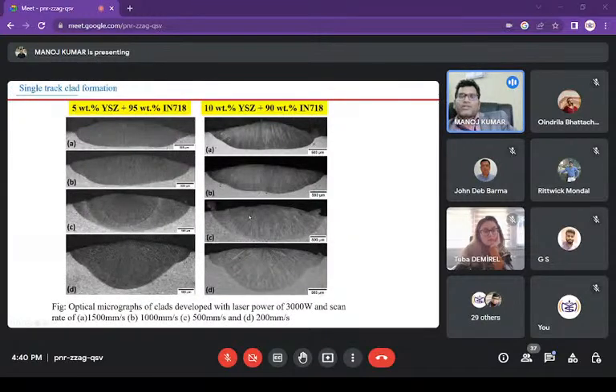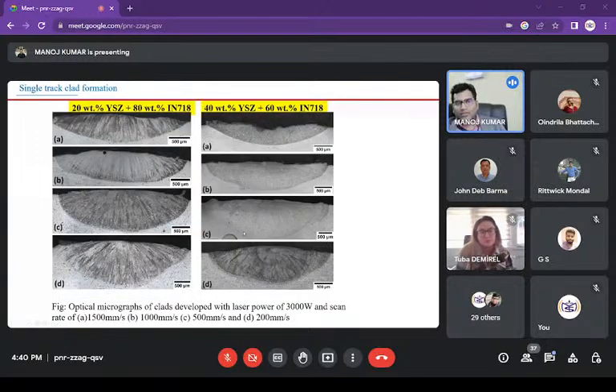So after deposition, we took a cross section of each. We deposited a single track, actually, for preliminary understanding of how the behavior changes with change of oxides and also the laser parameters. We see that when there is a high metallic component, 95% of Inconel 718 powder and only 5% YSZ, there is a very good clad. You can see there is a bulge of extra deposit of clad over here. You can see even a good clad is achieved at 10 weight % of YSZ. But when we slowly increase the YSZ, we see that deposition has reduced.